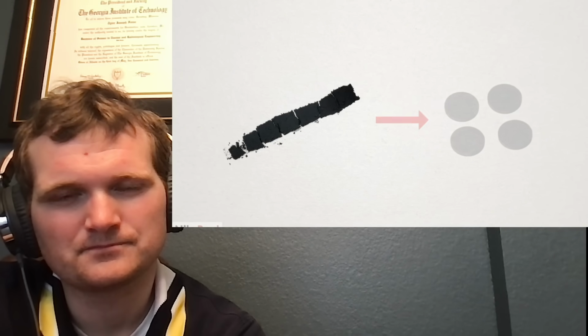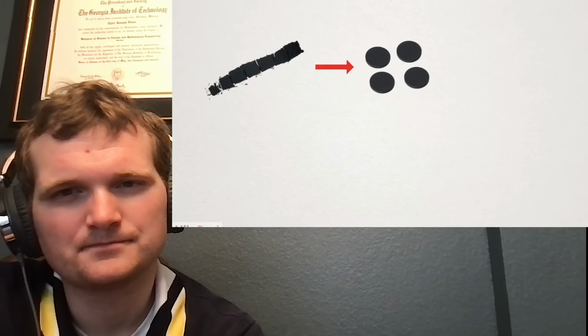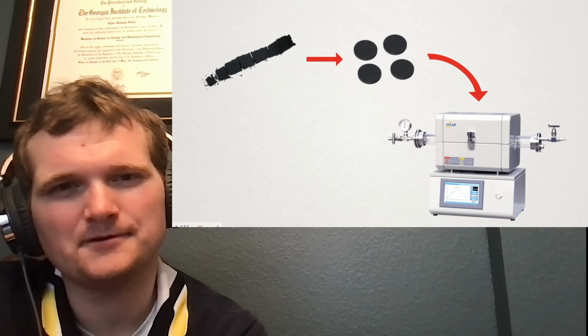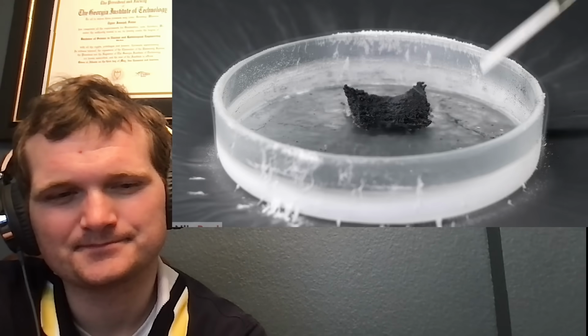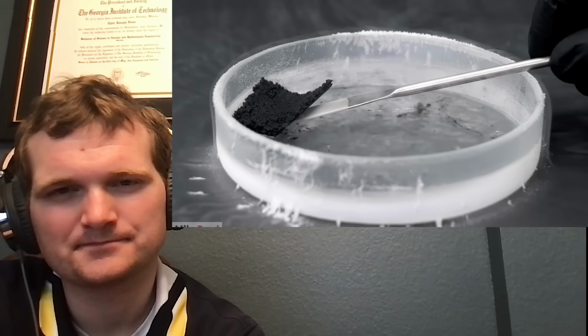To fix both these problems, the YBCO is usually compressed into pellets and then put back into the furnace and heated again with oxygen. So, that was exactly what I had to do next. To do this, I started by adding it all to a mortar and I ground it into a fine powder.